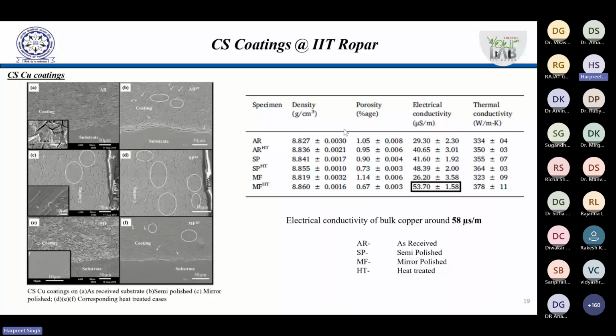That was the one research problem, because when we deposited on the as received substrates, we were not getting very good adherence strength, because one of the worries of coating engineers is how well the coatings are adhered to the substrate, right? So we have to do a lot of work in terms of getting required adherence strength with the substrate. For that we played extensively with the surface roughness of this substrate before coating, right? So we have to come up with different kinds of strategies to get better adherence on this surface. For example, here we used as received as well as semi-polished and mirror polished samples, right?